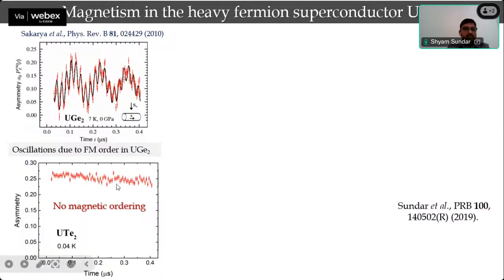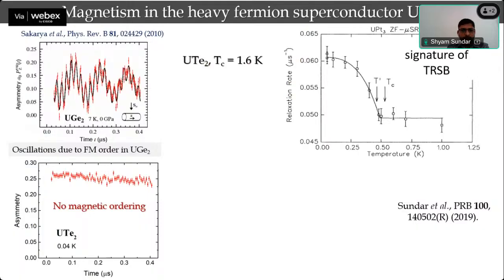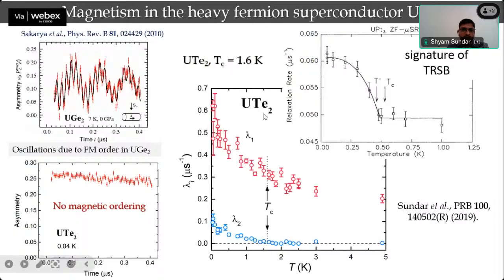So basically this tells there is no magnetic ordering in uranium ditelluride down to 40 millikelvin. And when we plot this to see the signature of time reversal symmetry breaking, as I showed you previously, its relaxation rate should show a spontaneous jump around Tc. But when we plot the relaxation rate as a function of temperature for uranium ditelluride, we did not see any spontaneous jump in the relaxation rate, rather this slowly increasing relaxation rate.